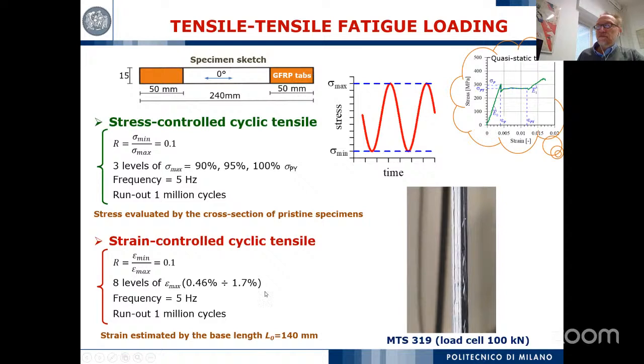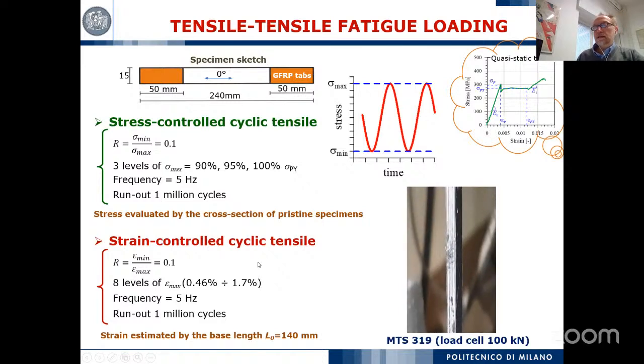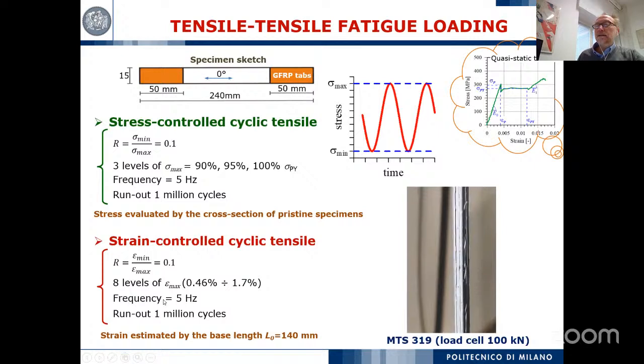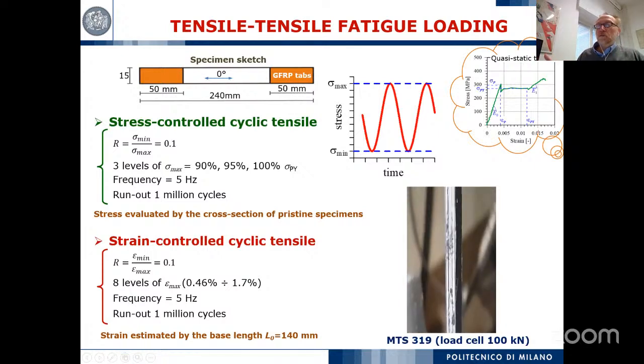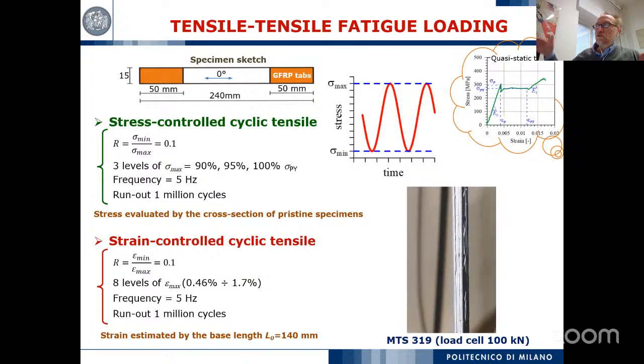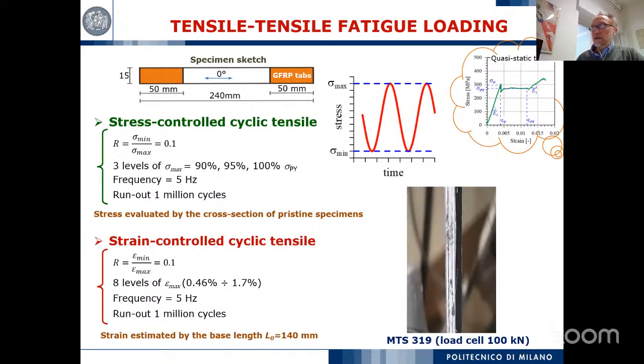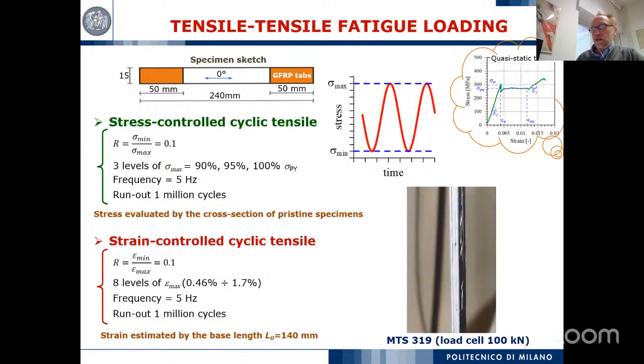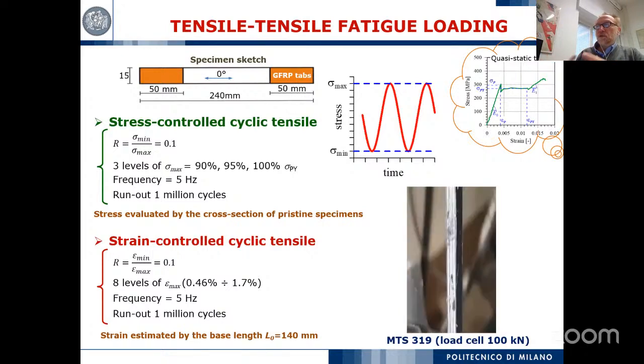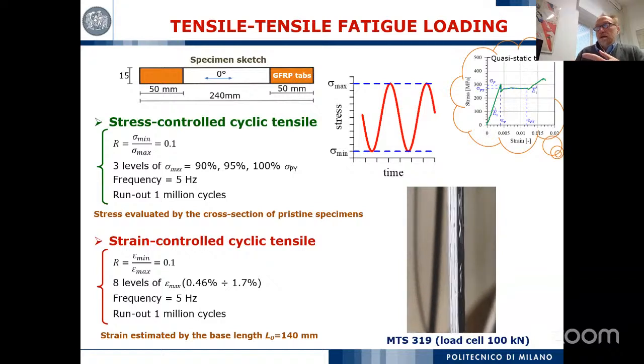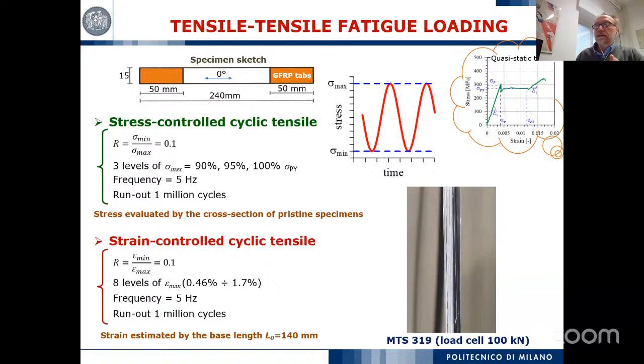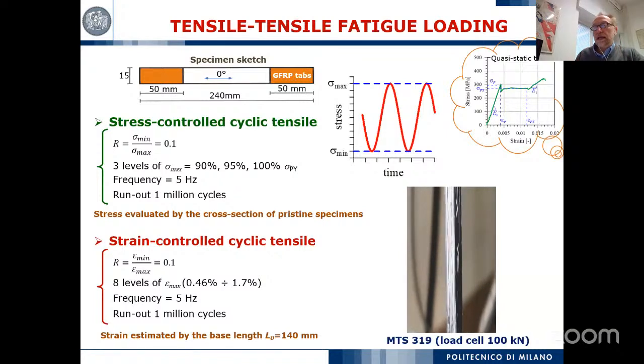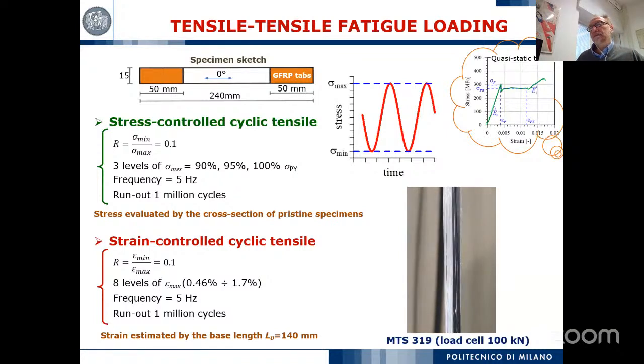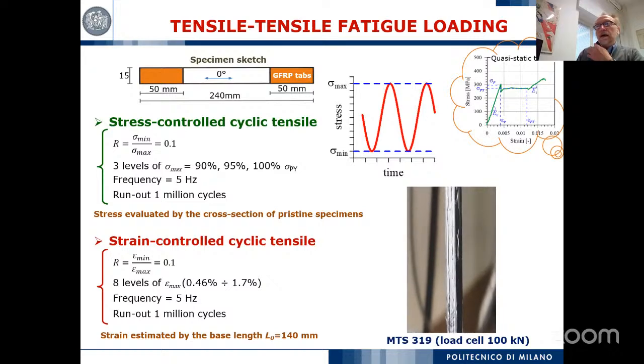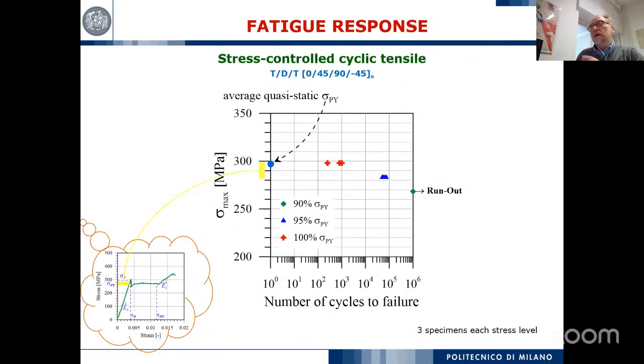And we have also strain control tests with 8 levels of strain from the beginning of the plateau to the second branch of the static stress strain curve. This helps us to understand if the pseudo-ductility can help us to sustain or to have longer fatigue life or not. Moving to the results in terms of stress control tests.